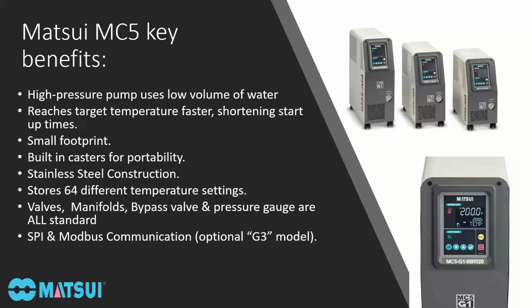Well, our MC5 unit uses a high pressure pump, which uses a low volume of water. So it's a high pressure pump. It reaches target temperatures faster, shortening startup times. It has a small footprint, which is important in our injection molding machine cell. It has casters for portability, stainless steel and copper components, and can store up to 64 temperature settings. It has valves and manifolds complete on the unit, so you don't have to worry about fabricating your own. The unit comes with the valves and manifolds already on it. It has a bypass valve and a pressure gauge as well.